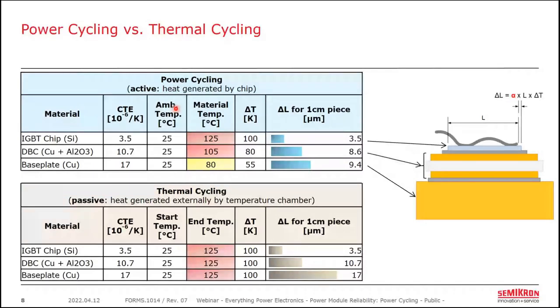The thermal cycling test, we do this as a separate test, and it's really intended to just evaluate the materials and construction. So I would look at these as two different tests. One is to try and look at realistic lifetime in an application. The other is to evaluate, again, construction techniques and things like that, because you're really artificially stressing the base plate. You're artificially stressing these in ways that you would not in the real application.